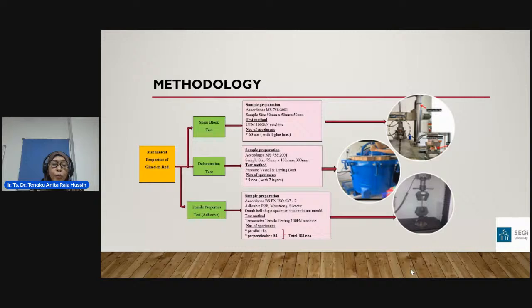All right, the second one is delamination test. Sample preparation is according to Malaysian standard 758/2001. The sample size is 75 millimeter by 130 millimeter by 300 millimeter. The test method is pressure vessel and drying duct. And number of specimen is 9 numbers.